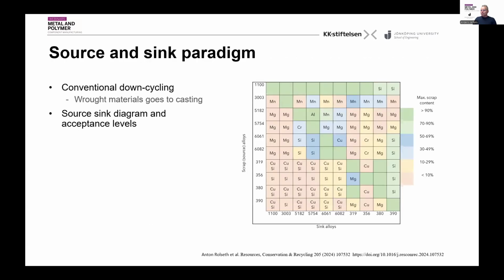Next, please, Esam. This is a source and sink diagram where you have the scrap source types on the left: 1100, 3000 series, 5000 series, 6000 series, and then your typical cast materials with 319, 356, 380, and 390 being the sources. And along the bottom, you have the sink alloys. If you take, for instance, 6000 series, 6061, you can actually produce an 1100 series material. But what will be limiting there is the copper and silicon content. And that limits it, as you can see from the color, so that you can take no more than 10% of this material because it's limited by the copper and silicon.